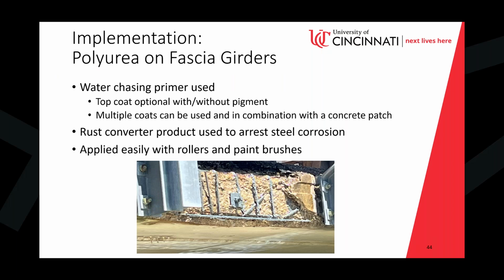So here is actually the finished product of the one that we had worked on. They did not opt to bother with applying a concrete patch. This was all just applied directly to the exposed concrete, instead of removing the bad concrete, getting to some good concrete, and applying it then.